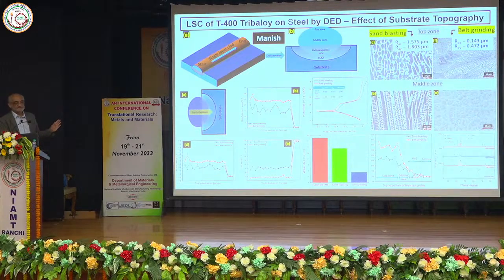Now whether it is sandblasting or belt grinding, a blind man can see the difference in the microstructure. Just because the surface preparation method adopted was different, the entire microstructure could be so much different. That taught us one lesson: we all tend to worry only about the laser, the power density, the speed, the composition of the powder, ignoring altogether the surface condition of the stock on which we are cladding or depositing. That also has a very large bearing.